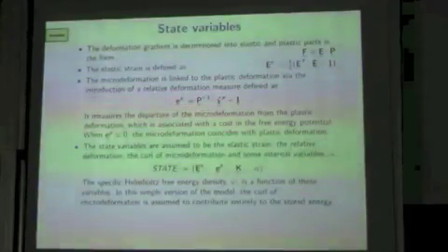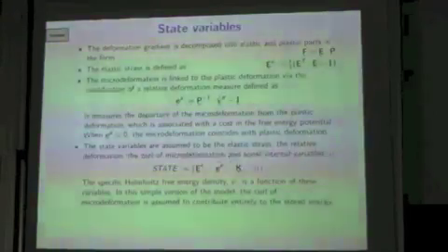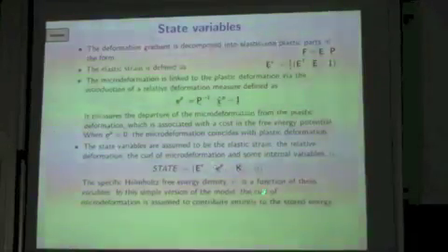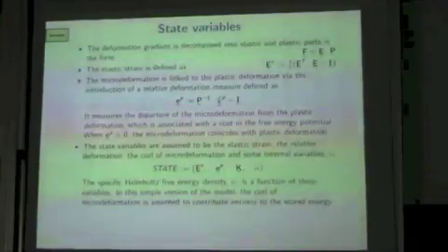So it means in this theory there is a price to pay for the micro deformation to be different from the plastic deformation. The state variables are the elastic strain, this relative deformation EP here, and the curl that we mentioned already. If you want, you can add your favorite internal variables for hardening, but coming from usual crystal plasticity.